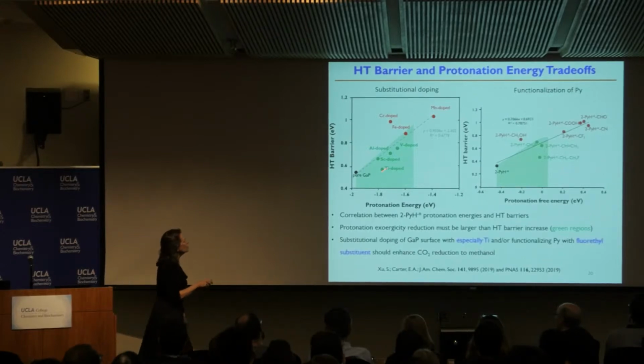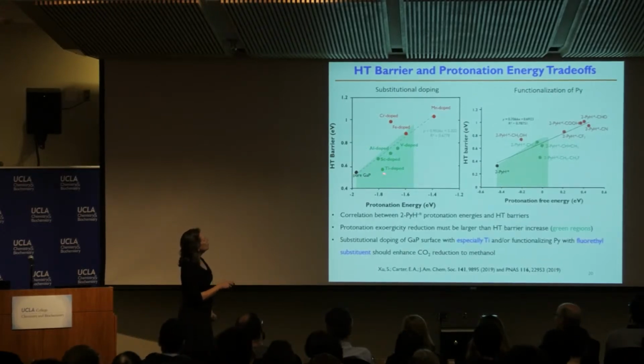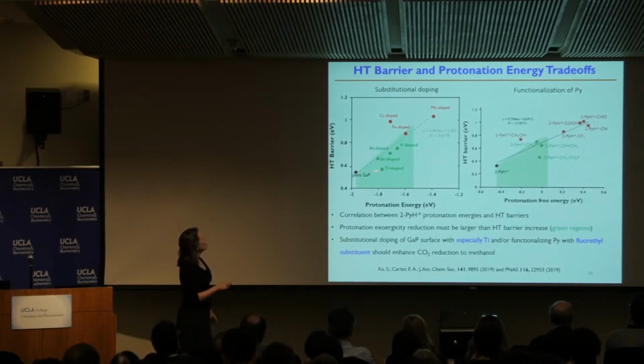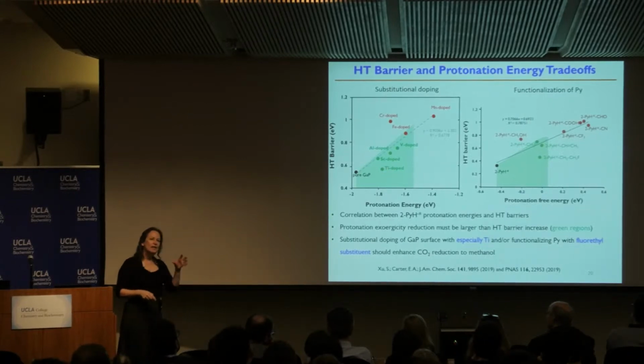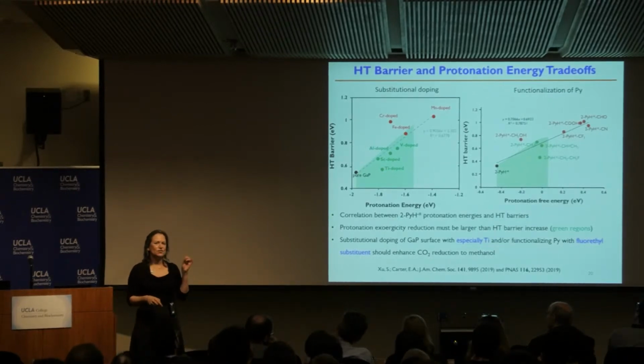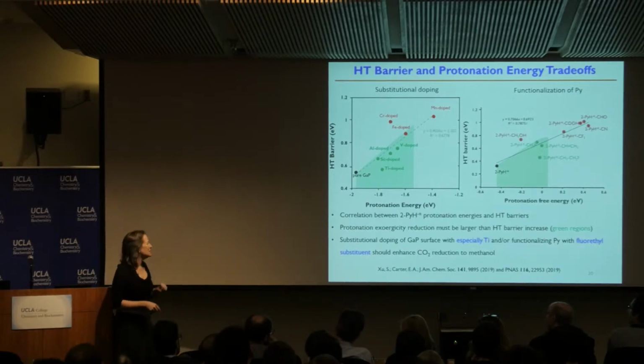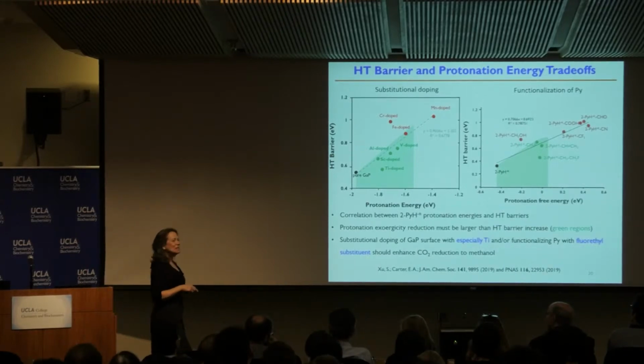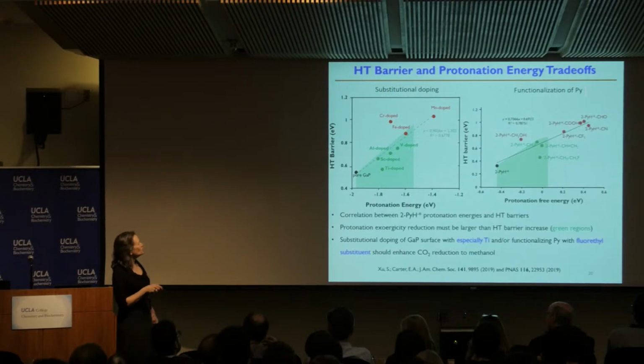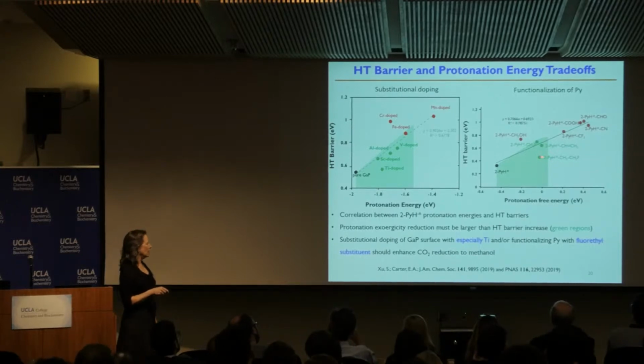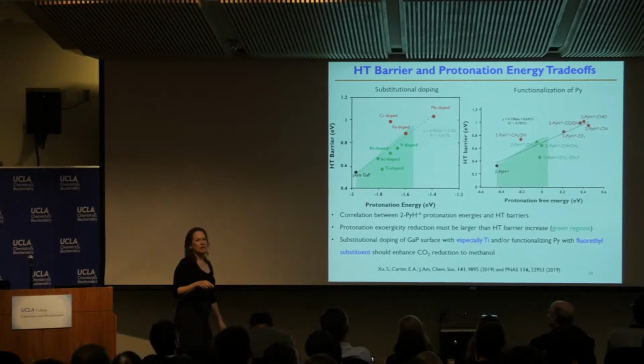And so you can see that you can move the needle on by doping with titanium quite a bit without paying a cost in the hydride transfer barrier. So we think that it's worth thinking about, is there a way to dope gallium phosphide at the surface, not easy, with titanium? A much easier thing for an experimentalist to do is to functionalize pyridine. And so what we see here, again, the best result is this fluoroethyl pyridine that we think should in fact enhance CO2 reduction to methanol.